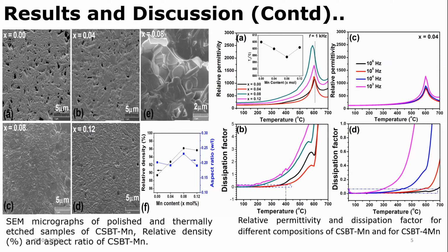And here towards the right side, you can see the relative permittivity versus temperature graph of different concentrations at a frequency of 1 kilohertz. These peaks verify that there is a transition from the ferroelectric phase to the paraelectric phase, and this also tells us about the Curie temperature. Here in the inside graph, you can see that TC first decreases, then increases.